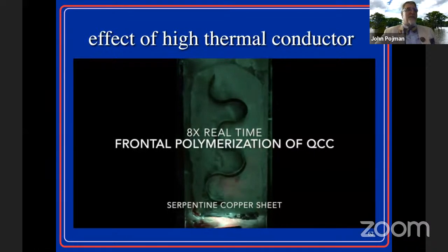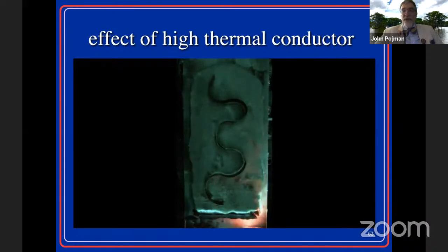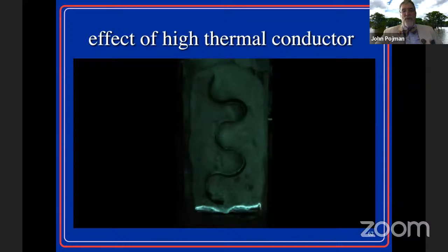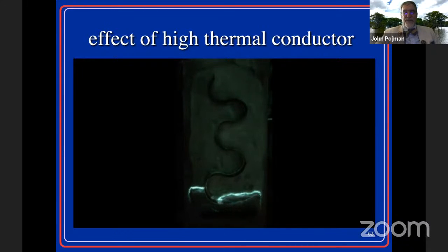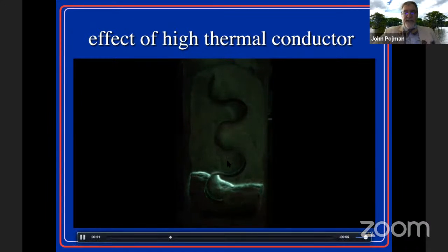But one thing we're doing now is how do we make these reactions go faster without changing the chemistry? And one way is to put in materials that conduct heat very well. And this has got extremely interesting, and these are fun experiments. These were done by a senior chemistry student. And you can see that where the copper is, the heat is conducted, and so it accelerates the front propagation. And all of these wave patterns, those are these complicated spin modes happening.